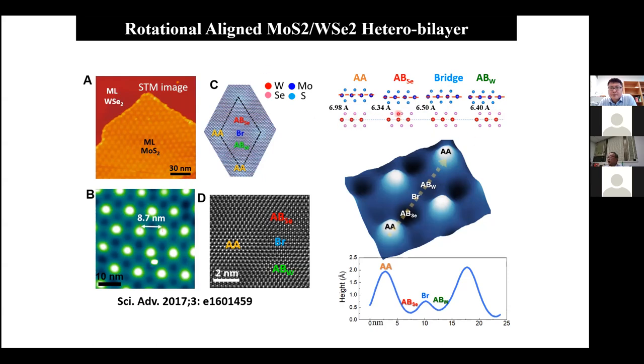So you compare this one, then you say, wow, the two agreed so well. I was shocked, right? How can DFT predict things so precisely? So we were happy and published this result. But we noticed that in the theoretical calculation, the modulation amplitude should only be about 0.6, 0.7 angstrom, while in reality, what we observe is more than 1.5 angstrom. But STM just measures the electronic structure, so it is always convoluted with the electronic effect. We are happy. So we say, well, the two agree so well.